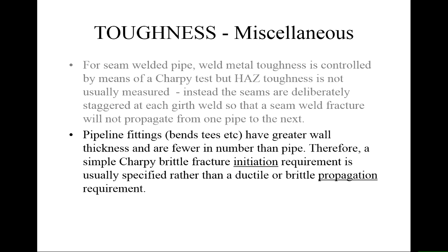Pipeline fittings, so bends, T-pieces, that sort of thing, generally have a greater wall thickness than line pipe. And they're fewer in number, and they're generally something that you can look at in a little bit more detail in the factory before, so you can look for defects, do non-destructive testing and things like that. So a simple Charpy test is sometimes specified on the material just to make sure that the crack initiation doesn't take place within that volume. So you specify just a Charpy test for initiation. You don't worry too much about crack propagation.